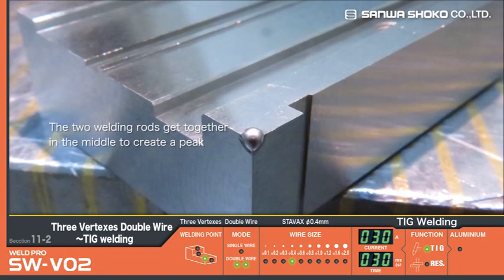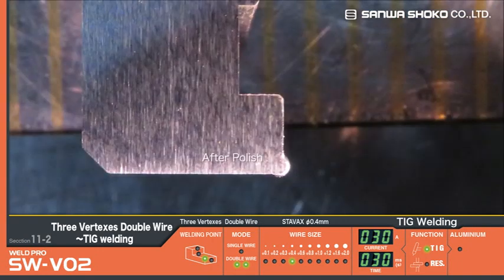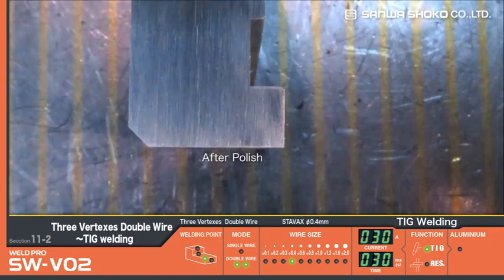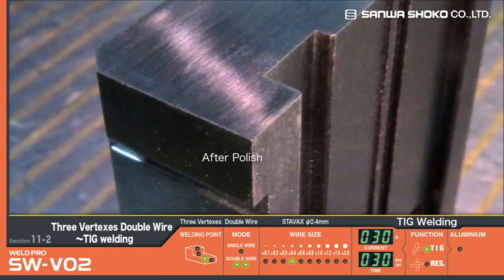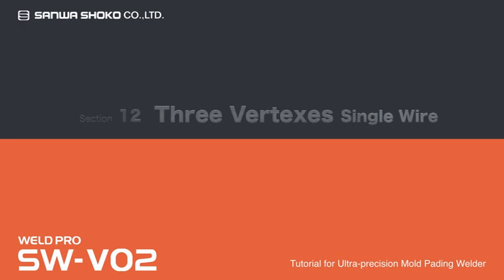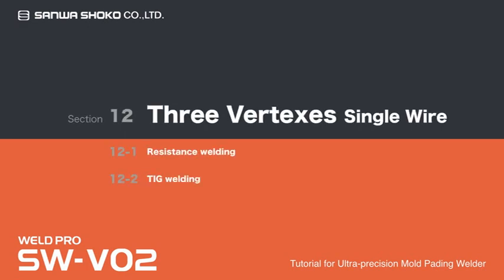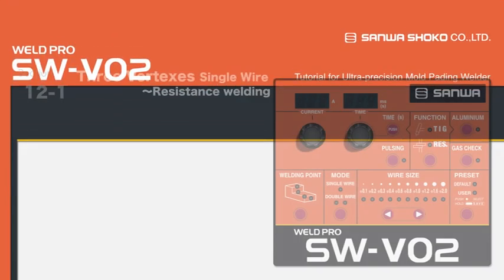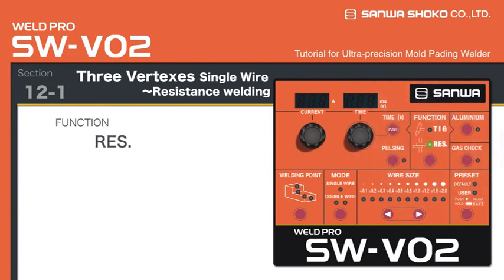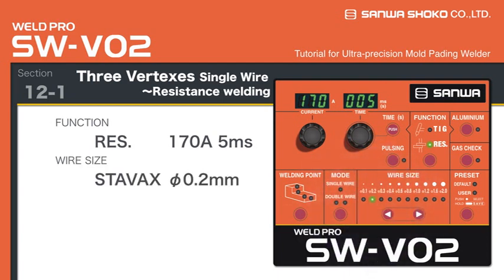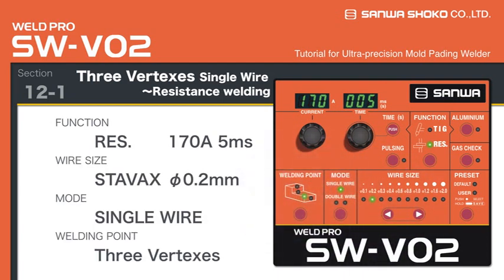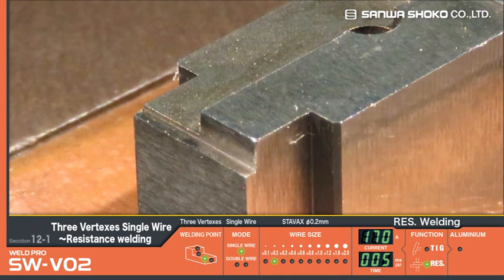The two welding rods get together in the middle to create a peak. Even though the welded area is polished, it can be confirmed that no shrinkage is observed. Now, three vertices are welded in a single wire mode. A torch stand is used in this case.